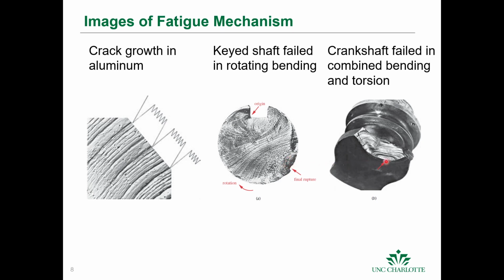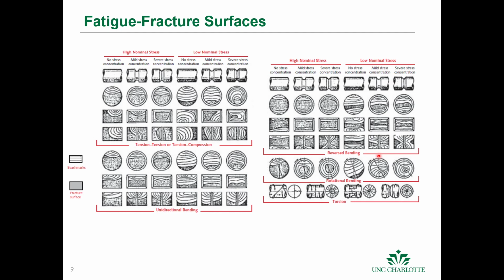This is another view. This is a crankshaft subjected to bending and torsion. Again, you see those marks and how the cracks propagate through the surface until finally it fractures off. It turns out that the patterns left behind from a fracture are related to the type of bending, and this is a graphic from your book which shows how the crack propagates through a surface with different loading conditions. And so this here is a tension or tension-compression mechanism.